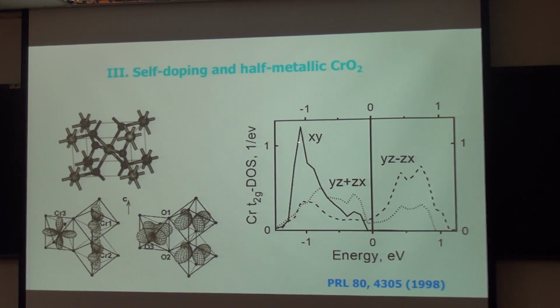One is localized, the so-called dxy, and another is partially occupied, YZ plus ZX or YZ minus ZX, depending on the crystal site of the chromium. So this partially occupied as well as the localized, fully occupied state provide a double exchange picture that is the origin of the so-called half-metallic electronic structure.